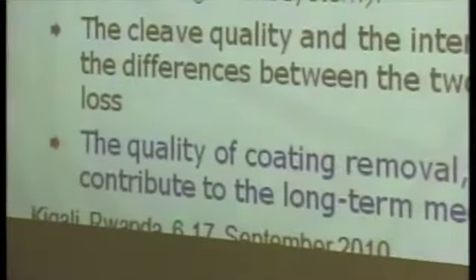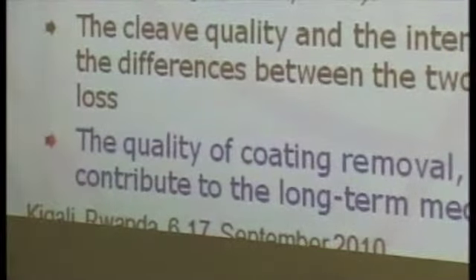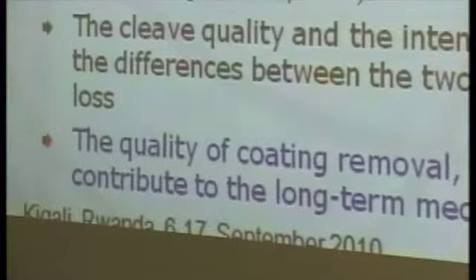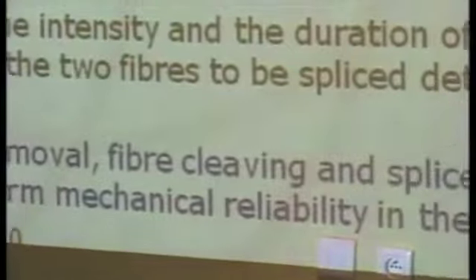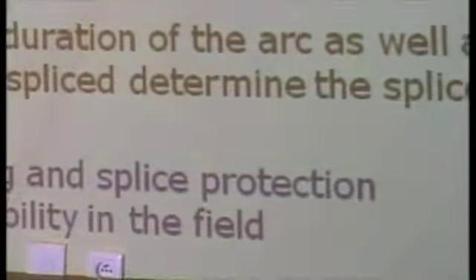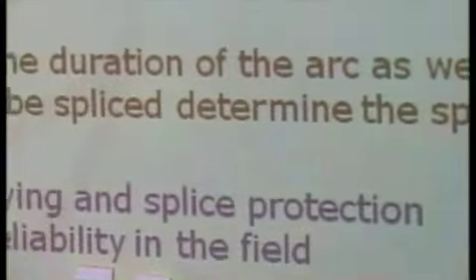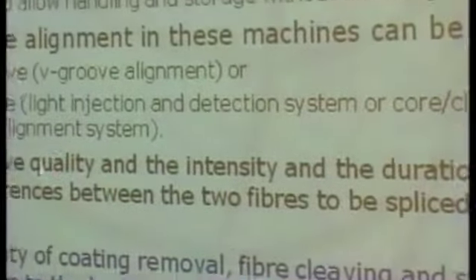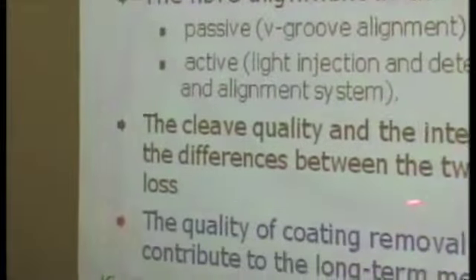In terms of loss, these are the more important things to have in mind. In terms of long-term mechanical reliability, it's necessary to remove the coating with some care, clean the fiber with some care, and also protect the fiber in a good way, because this aspect refers to the quality of the optical interface, and this aspect refers to the quality of the glass surface. The new fiber interface will give us the loss, higher or lower, and the quality of these procedures will make damage or not in the surface of the fiber, and will allow the fiber to keep working well for a long period or not.